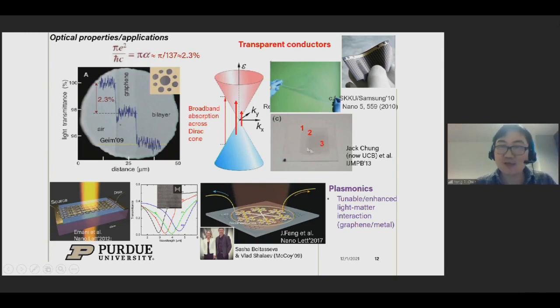Here's also a quick example from my lab. You can stack multiple of these layers, then they consecutively absorb multiple units, multiples of these 2.3%. We also had a very fruitful collaboration in the last few years with Sasha Boltasseva and Vlad Shalev in engineering here at Purdue, exploring the plasmonic properties of graphene based on these very large chemically synthesized graphene, which we can incorporate with the metal plasmonic structures, and their optical properties or plasmonic properties are tunable by structure shaping or electrical gate voltage. So this very strong and tunable light-matter interaction enabled by these synthetic graphene together with the metal is another very interesting application of these graphene materials.